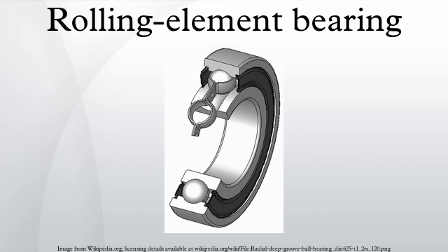Although there are many other apparent causes of bearing failure, most can be reduced to these three. For example, a bearing which is run dry of lubricant fails not because it is without lubricant, but because lack of lubrication leads to fatigue and welding, and the resulting wear debris can cause abrasion. Similar events occur in false brinelling damage. In high-speed applications, the oil flow also reduces the bearing metal temperature by convection. The oil becomes the heat sink for the friction losses generated by the bearing.